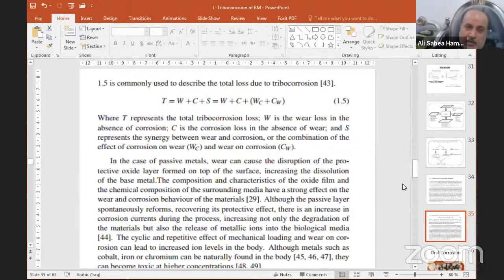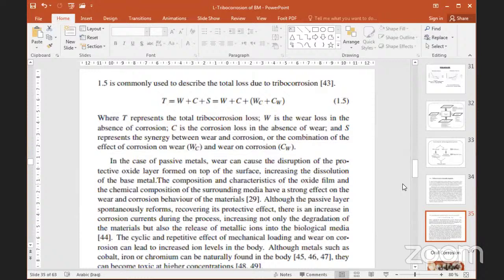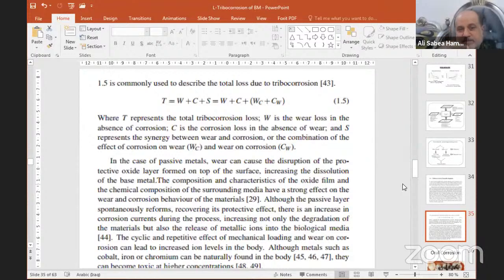Yes. Thank you. T equals W plus C plus S, where T represents the total tribocorrosion loss. W is the wear loss in the absence of corrosion. C is the corrosion loss in the absence of wear. But S represents the synergy between wear and corrosion at the same time, or the combination of the effect of corrosion on wear and wear on corrosion: W plus C plus WC plus CW. This equation is very important.